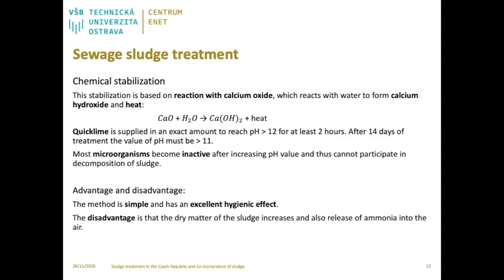Chemical stabilization. This stabilization is based on a reaction with calcium oxide, which reacts with water to form calcium hydroxide and heat. Quicklime is supplied in an exact amount to reach pH higher than 12 for at least 2 hours. After 14 days of treatment, the value of pH must be more than 11. Most microorganisms become inactive after increasing pH value and thus cannot participate in decomposition of sludge.